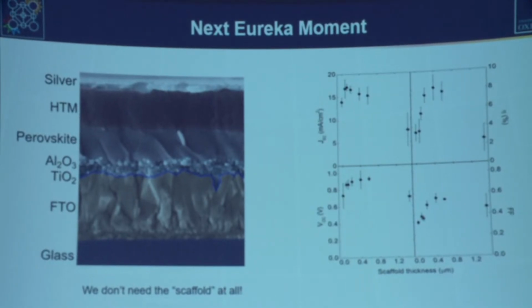So when doing some cross-sectional electron microscopy that I show here, what we found was the porous alumina - this bottom layer is the conductive oxide, a metallic but transparent metal oxide. We've then got the porous alumina, and then this layer is the perovskite. So what we found was the perovskite was filling this porous alumina, but then forming a solid continuous layer on top. This top thicker layer is our hole conductor material, our p-type charge extraction layer.